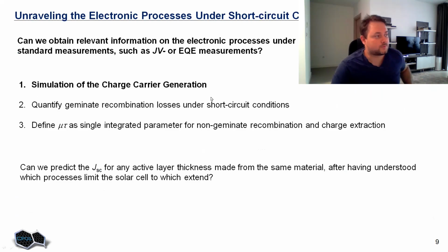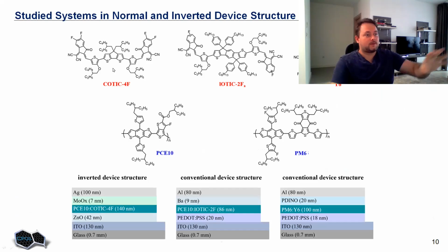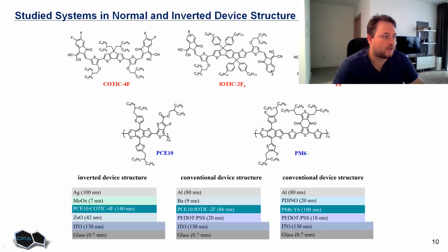So let us focus first on the simulation of charge carrier generation, which actually stands for exciton generation in the active layer. We picked different systems, so we have 3 non-fullerene acceptor materials and 2 donor materials. We had different combinations of these materials in different device structures. So we have the so-called inverted device structure, where the cathode is on the side from which the sun approaches the solar cell, with zinc oxide working as the cathode, and the conventional device structure, where the anode stands first on the path of the sun when it hits the solar cell.